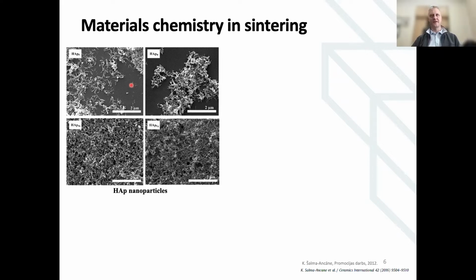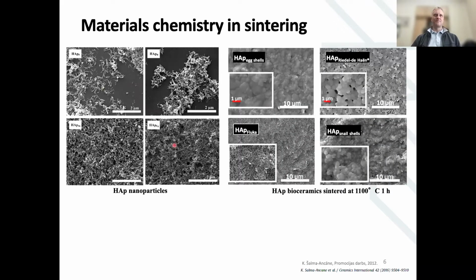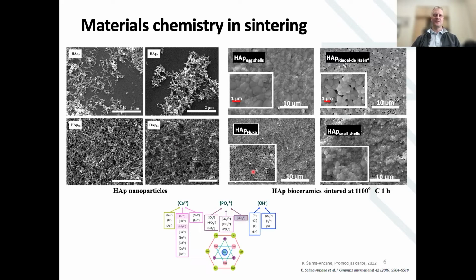that everyone was doing, and is still doing for many years, is sintering. And as we do the sintering of those calcium phosphates, hydroxyapatites, we do all of them at the same conditions, 1100 degrees for 1 hour. And what we find out is that there is a really big difference in the microstructure. And now the question comes, why? Why is there this huge difference? And the answer is pretty simple: in the raw materials which I showed you before, the eggshells, snail shells, or even the commercial ones, they are never pure. Or let's say, if you want to get a really pure one, then you have to pay a lot of money for that. But from the normal sources, they are not pure. And also, at the same time, the hydroxyapatite in bones is not pure, as was shown in the formula before.